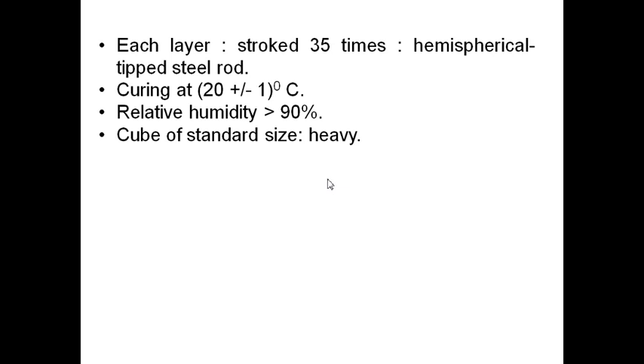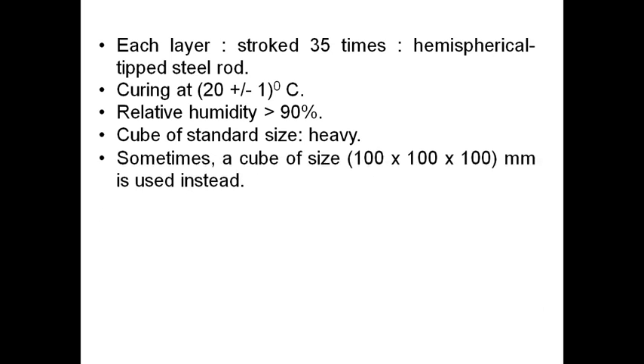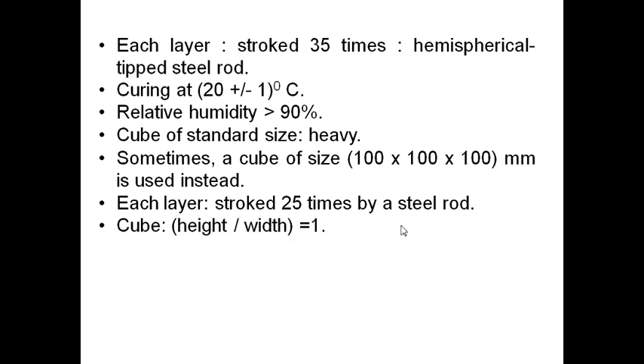The cube of standard size 150 × 150 × 150 mm is normally heavy, and therefore sometimes a cube size of 100 × 100 × 100 mm is used. Each layer is stroked 25 times by steel rod in this case, instead of 35 times. Since it is a cube, height by width ratio is 1.